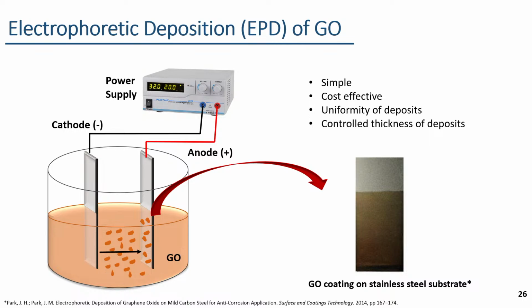Another promising application of graphene oxide is its use as thin films or coatings. Among different deposition techniques, electrophoretic deposition, that is EPD, is widely used to fabricate GO coatings with high homogeneity and controlled thickness. This is highly important for applications to control the coverage and the film properties with consistency.